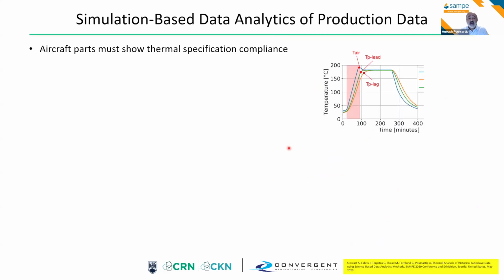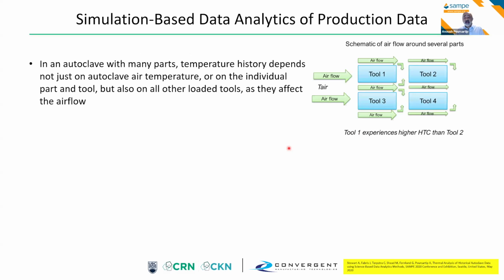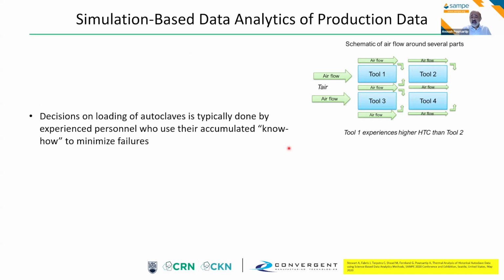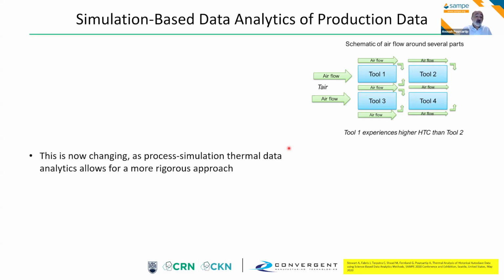This has been pushed increasingly into production. Remember, every aircraft part must show thermal compliance. So you've got to show that it's within a range of temperature increase, temperature hold, and so forth. And the problem is that very often, especially when you're making lots of little parts, the airflow interferes with all the parts in there. And so you end up getting very complex airflows depending on what you have in the autoclave that day. To date, this is typically dealt with by having experienced personnel who use their accumulated know-how. Clearly, we want to go past that.